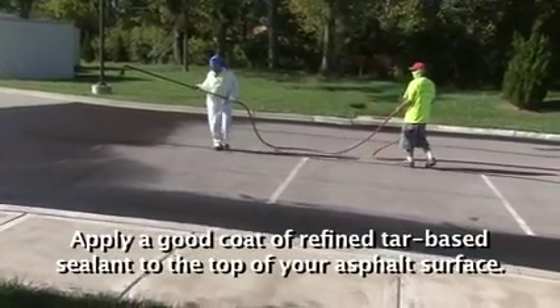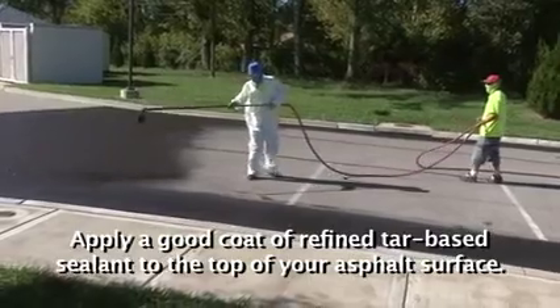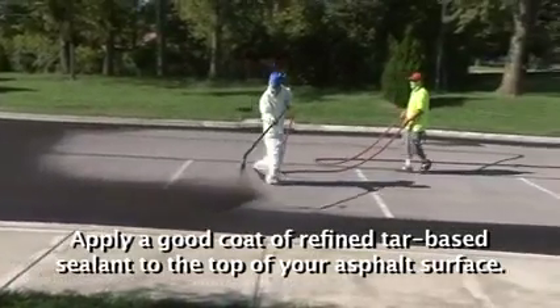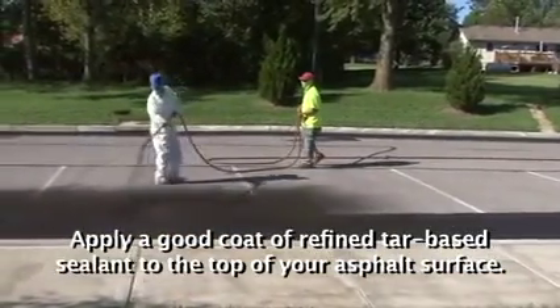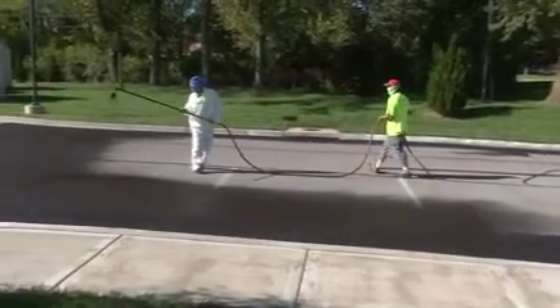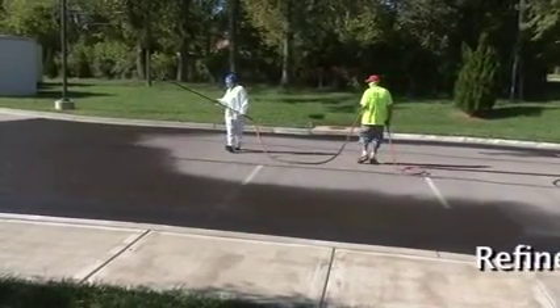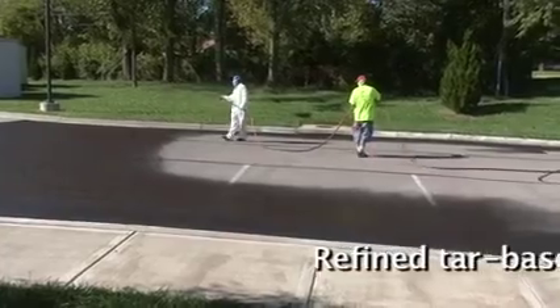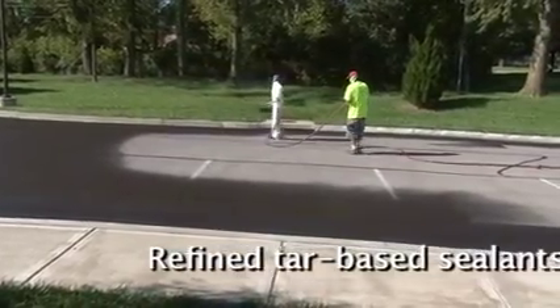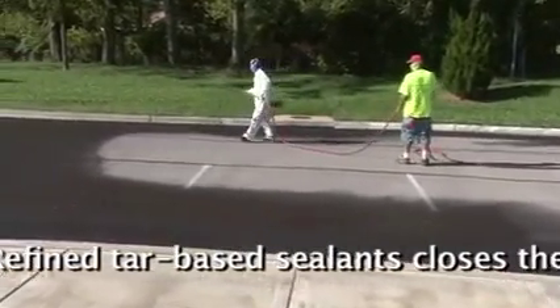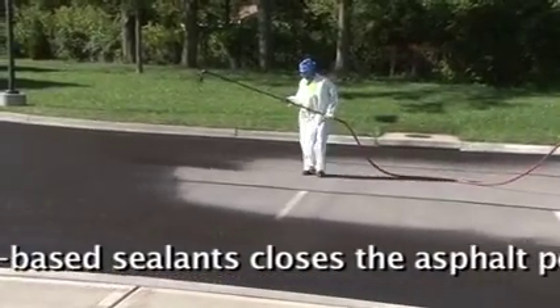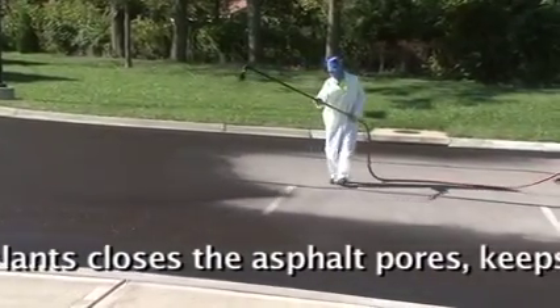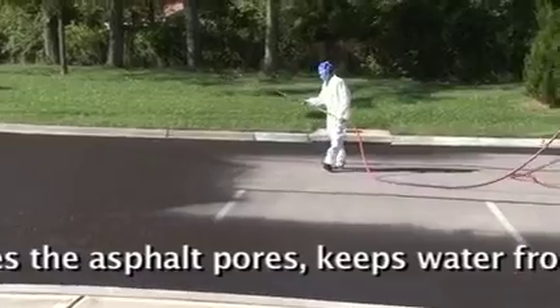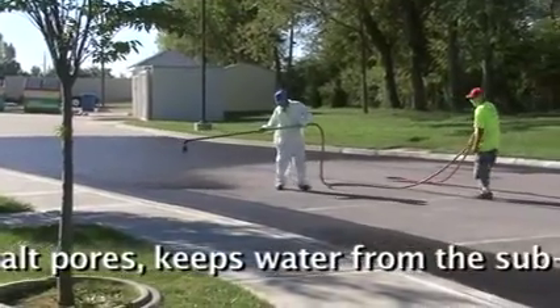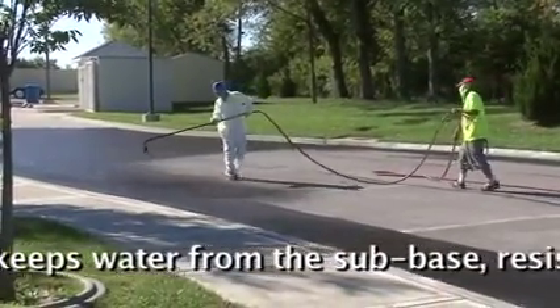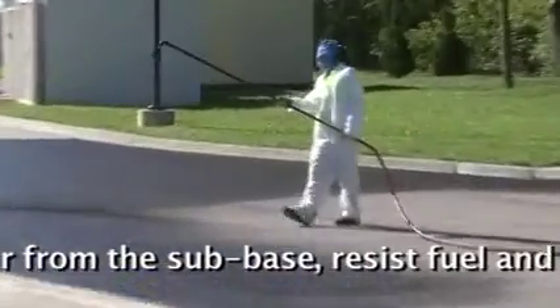And I don't have any qualms going back to the fact that the seal coating itself, to me, is a refined tar-based sealant, because it does the three things that we want it to do. We want it to keep the water out; it closes the pores of the asphalt to keep the water from getting to the subbase. It's also fuel resistant and oil resistant, because unlike an asphalt emulsion-based seal, if I pour gas or oil on an asphalt emulsion seal, it's going to eat right through that seal and go right into the asphalt.